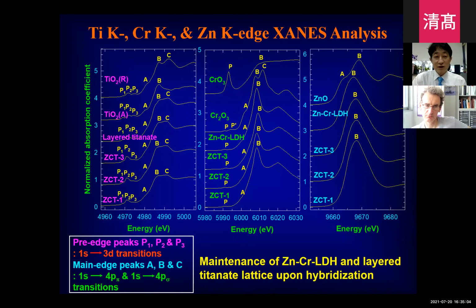Also, we applied XANES analysis, because the beauty of XANES is the easy identification of the phase. Even for the same tetravalent titanium oxide, each structure shows a unique XANES spectral feature: the rutile structure, anatase, and the layered structures. So it is very easily distinguishable. The nanohybrid shows the typical spectral feature of the layered titanate. So from that, we can confirm the maintenance of the layered titanate lattice after hybridization.